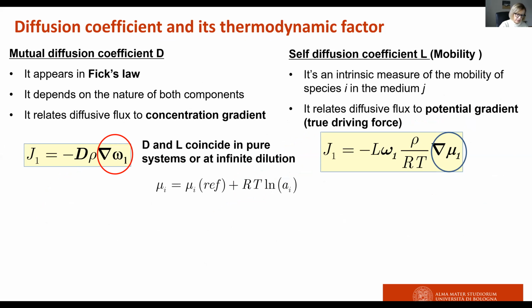Another story is the diffusion coefficient. First of all, we have to distinguish between the mutual and the self-diffusion coefficient, which also goes under the name of mobility. The first one is the most common form of diffusion coefficient, the one that appears in Fick's law and relates the diffusive flux to the concentration gradient, which is a very convenient quantity to be measured. Actually, the true driving force for diffusion in the membrane is not the concentration gradient, but rather a chemical potential gradient.